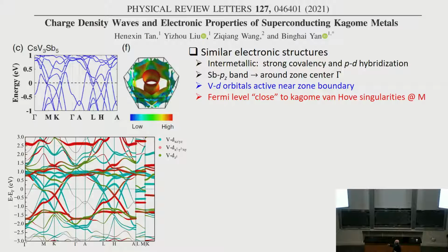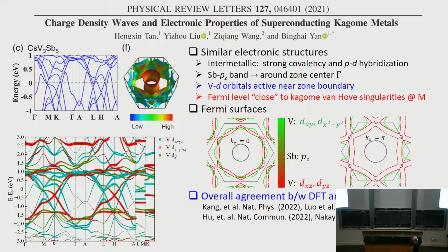The Fermi surface looks like you got a pocket in the middle. That comes from the antimony pz orbital. That's probably boring. Most of the d orbitals are active near the zone boundary. But indeed, the Fermi level is quite close to the Van Hove singularity. That's a landmark of these materials. The Fermi surfaces are given here.